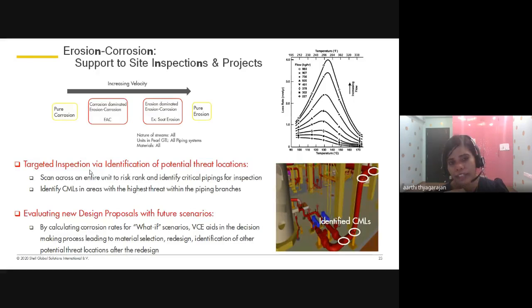So this is another example where the VCE augmented model for erosion corrosion has successfully demonstrated the following through working examples. We were able to screen the entire plant to identify the potential regions where they are susceptible. Secondly, we were able to predict erosion corrosion rates in the presence of relevant inspection data. And we were also able to rank the severity of erosion corrosion in different piping systems within a pre-identified vulnerable unit in the absence of any inspection data. So, it's always about what knowledge and what information doesn't exist, and where we can add value by combining the models with the data. That has been our important focus, so that we can really help these assets. Yeah, next slide please.